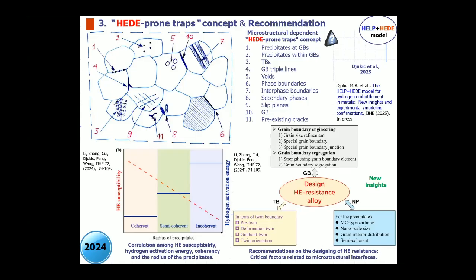And we recently, together with Chinese authors, published a paper in the International Journal of Hydrogen Energy last year, in which we give an analysis of designing improved hydrogen embrittlement resistance based on the effects of hydrogen on three types of microstructure feature, whether they are prone or not. We investigated twin boundaries in metallic material. We investigated what's going on with grain boundary and with nanoprecipitates. These nanoprecipitates are very important for strengthening high strength alloy. And we show the effects of coherence between precipitates and phase, in which the semi-coherent relationship is the most beneficial for the improvement of hydrogen embrittlement resistance of the material.